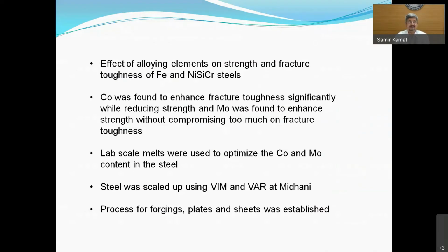He found that cobalt significantly enhanced the fracture toughness, but it reduced strength. Whereas molybdenum increased strength without compromising too much on fracture toughness. So he then tried various lab scale melts to optimize the cobalt and molybdenum content in the steel, that is the nickel silicon chrome steel. And after a series of experiments, he was able to identify a suitable composition which more or less met the requirements of the properties of maraging steel.